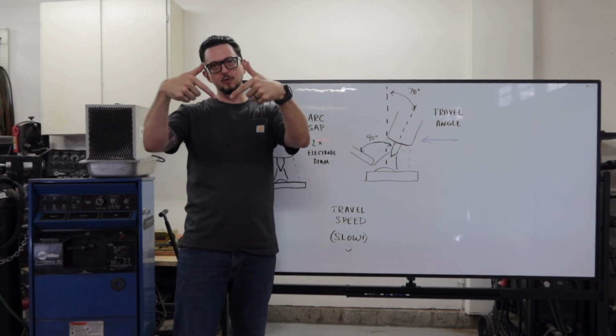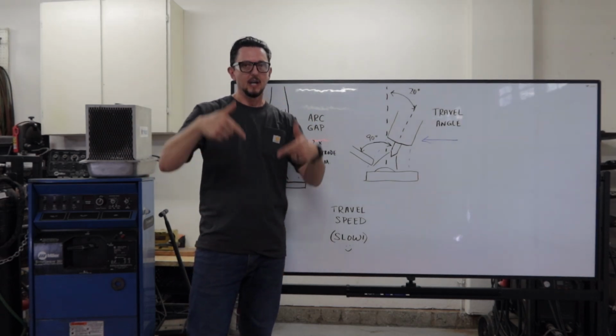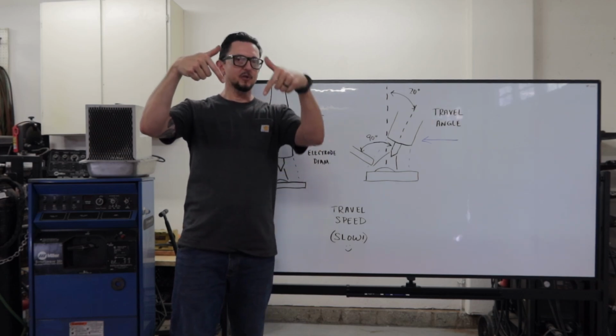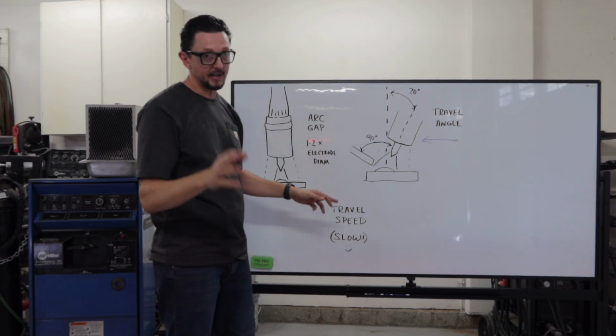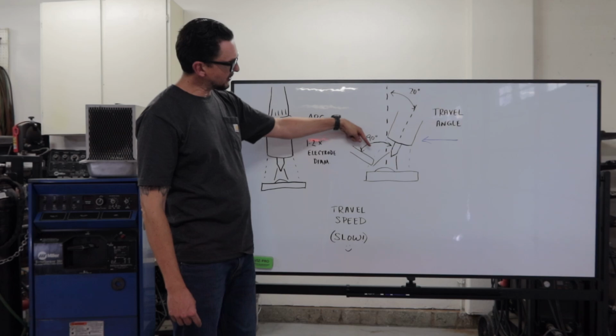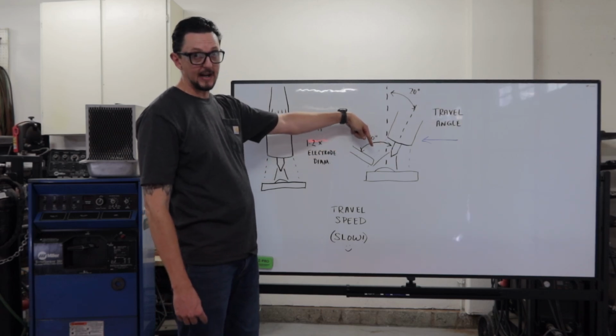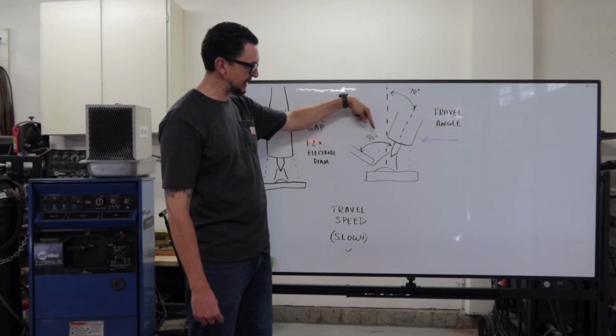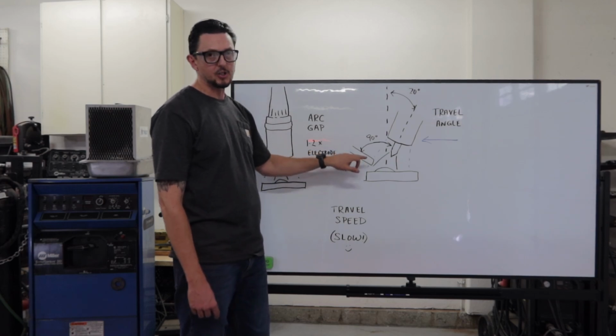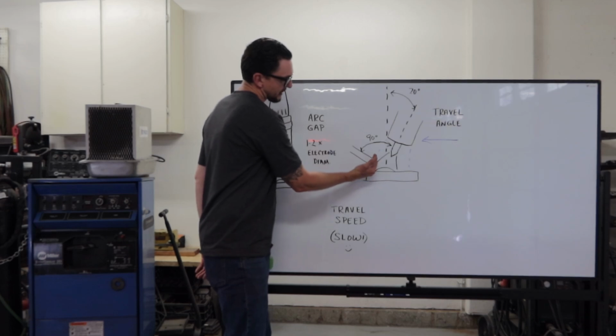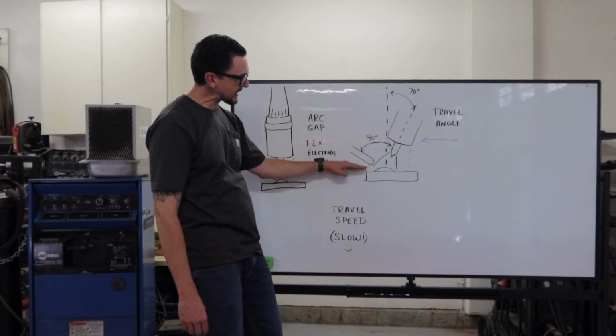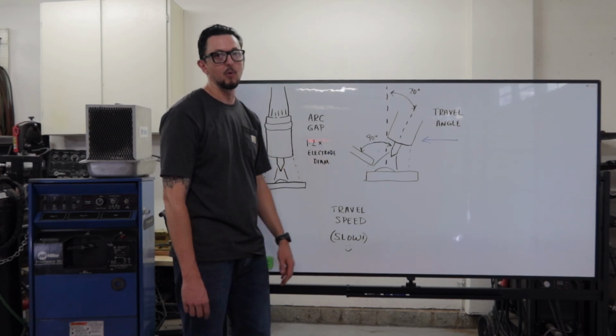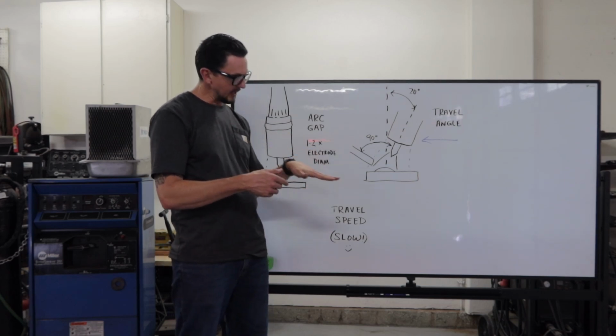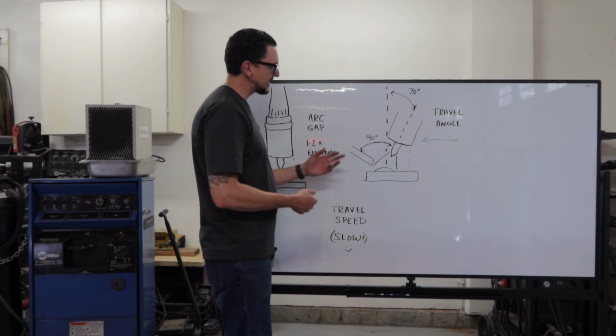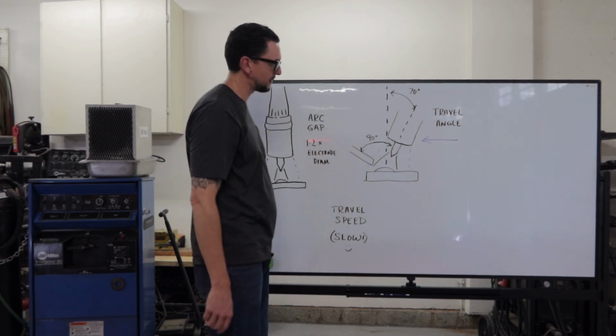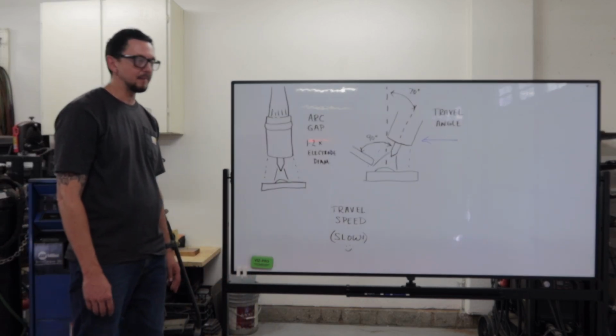And that's relative depending on what type of joint you're doing, what type of position you're doing, and all that kind of stuff. You just don't want too extreme of an angle with your electrode. I'm sorry, your filler metal. The angle of your filler metal will actually determine how much filler metal you're adding. So the higher you go with this filler metal dipping into the weld pool, the less filler you add, because you're taking a smaller cross section of that filler metal. As you put it flatter, you're actually adding more, because you're able to dip in more of that filler at a more gradual angle. So just keep that in mind. But to start off with, about 90 degrees to the electrode itself is where you want to keep it.